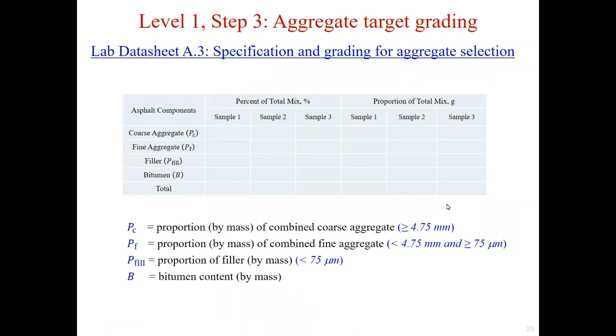We could also work out the proportion of combined coarse aggregate PC, the proportion of combined fine aggregate PF, proportion of filler PFill, and bitumen content capital B. Be aware that PC is for coarse aggregate with particle size equal to or greater than 4.75 millimeter.